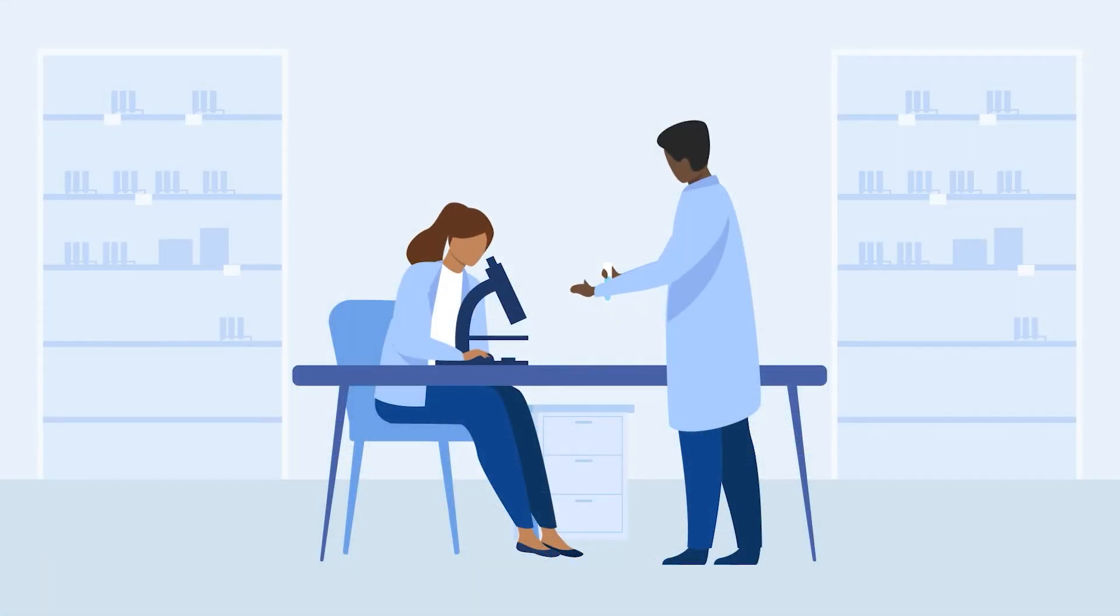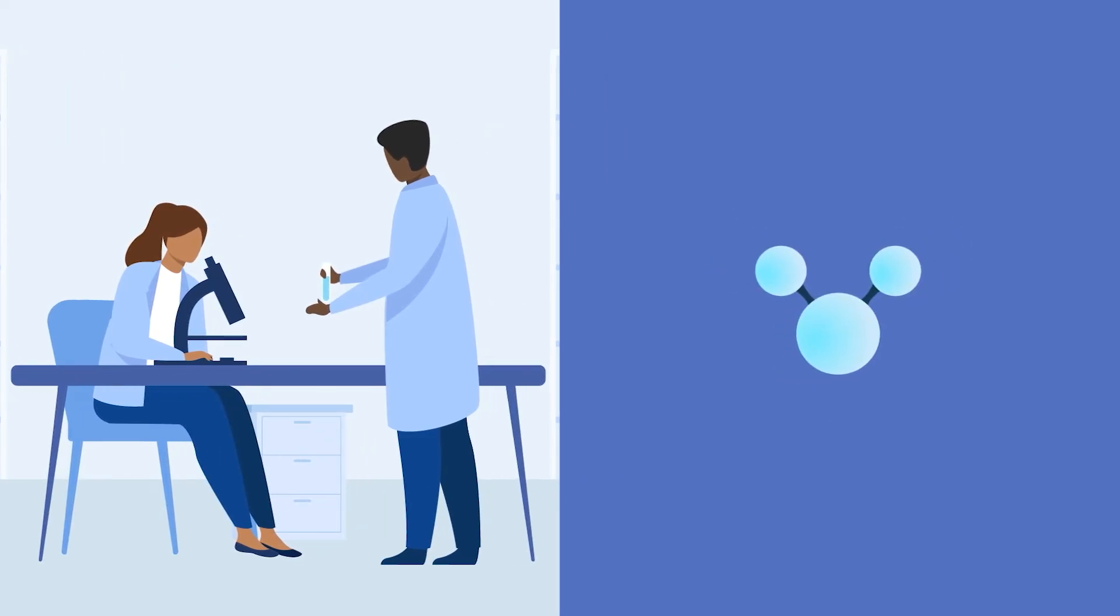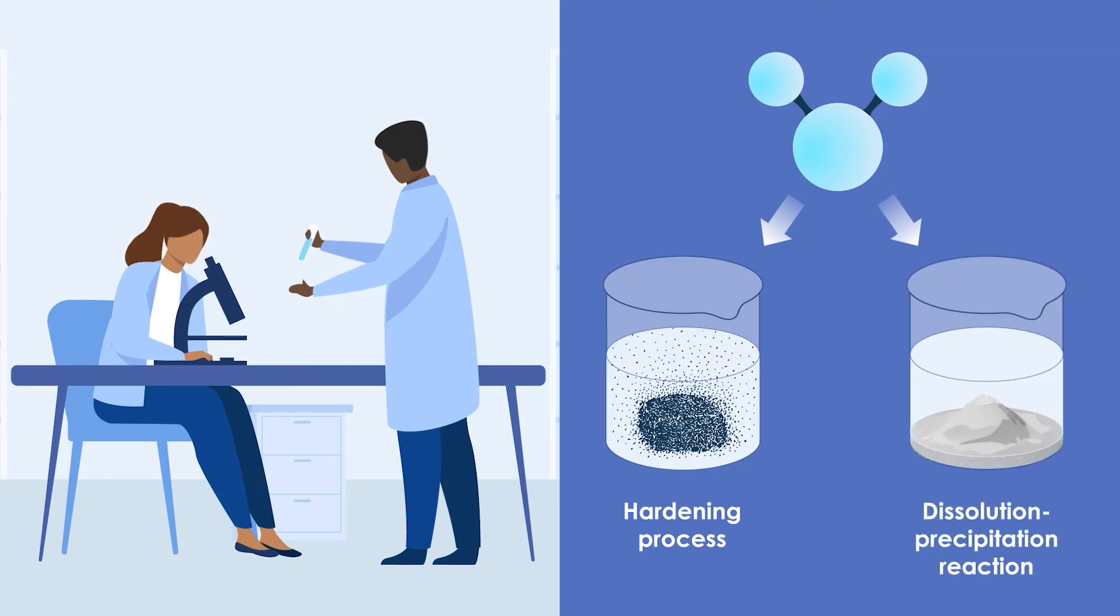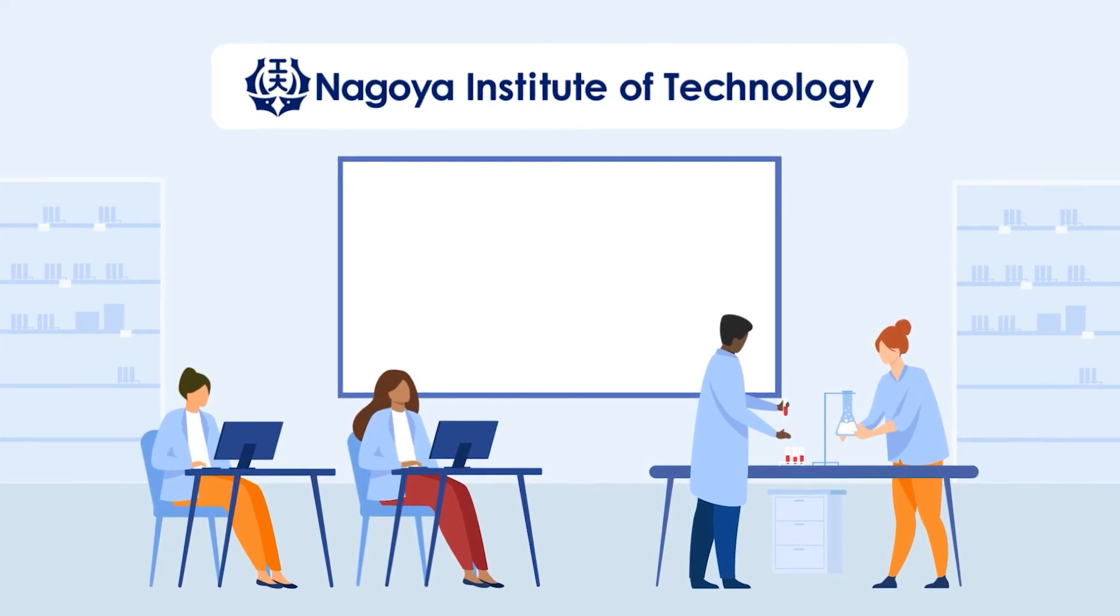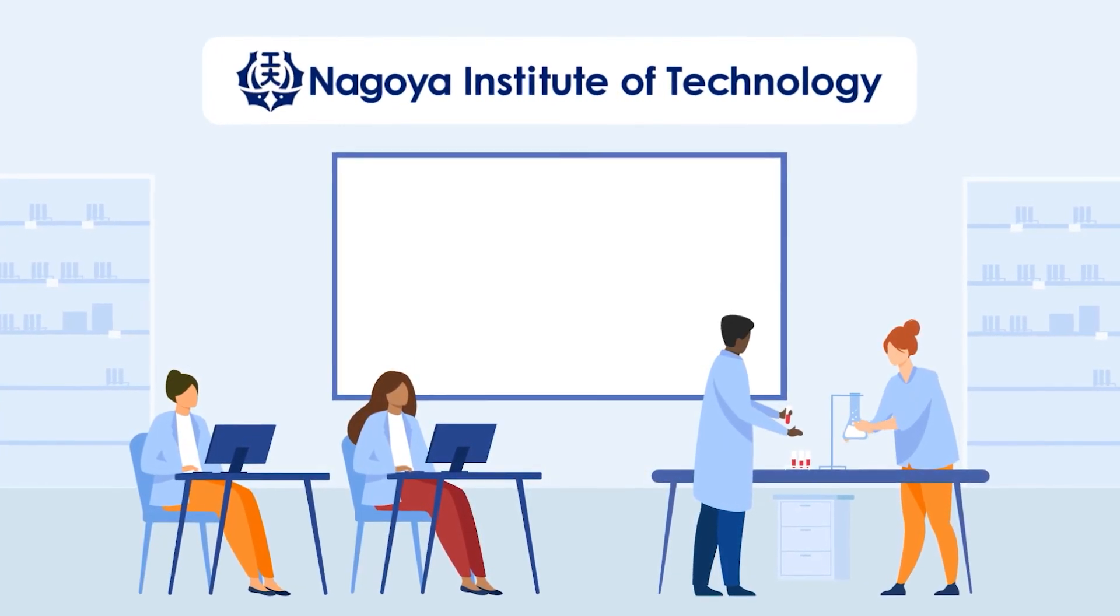The team used water as the solvent for their experiments and observed that water played a crucial role in promoting the hardening process that occurred via a dissolution precipitation reaction.